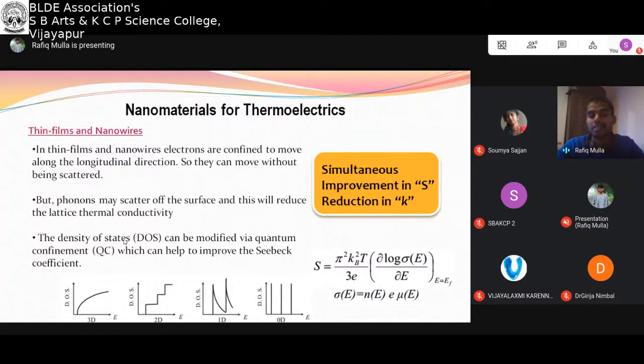And another important aspect is, as we have seen in our previous lecture, the density of states is going to be modified when we go from bulk to nanostructures. And if we consider quantum well, or this is thin film, and quantum wire, the density of states is entirely different as compared to the normal bulk one. So here we can see a drastic change of density of states with respect to energy. Here also a drastic change of density of states with respect to energy. Whereas there is a smooth change in density of states with respect to energy in case of bulk semiconductor.